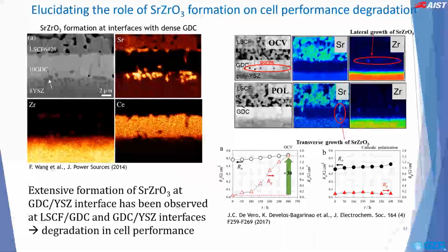A prime example of secondary phase formation in typical SOFCs is strontium zirconate. This arises from the chemical reaction between a common cathode material, LSCF, and YSZ, a state-of-the-art electrolyte. Here, gadolinium-doped ceria, or GDC, is utilized as a barrier layer between LSCF and YSZ. The SEM-EDX images on the left-hand side show the cross-section of the diffusion triplet, which was annealed at 1200 degrees Celsius for 168 hours. Here, we can see the formation of strontium zirconate on either side of the dense GDC layer, indicating that strontium from LSCF and zirconium from YSZ have mutually diffused across the dense GDC layer and reacted to form strontium zirconate.